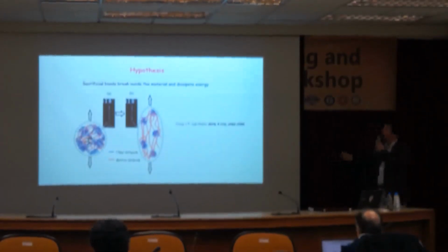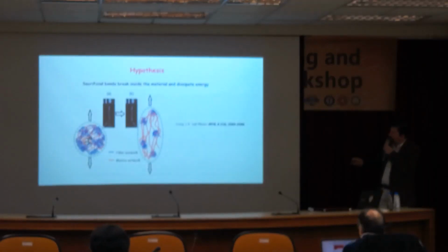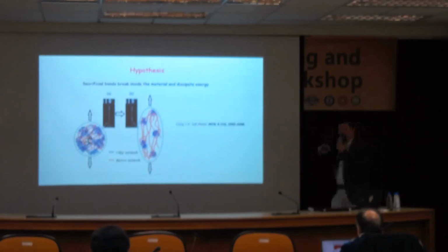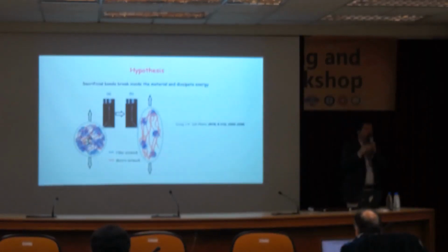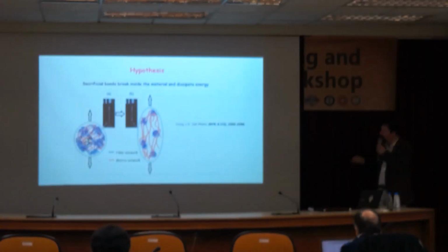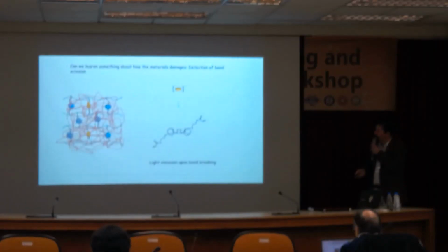Gonzalez speculated that this was due to sacrificial bond breakage inside, and that you had these blue, they also use blue for the hard material. The blue domains were actually breaking up into pieces. So their picture was that before this yielding process, one of the two networks was intact, and then after the yielding, it was broken in different pieces. So we were examining this hypothesis.